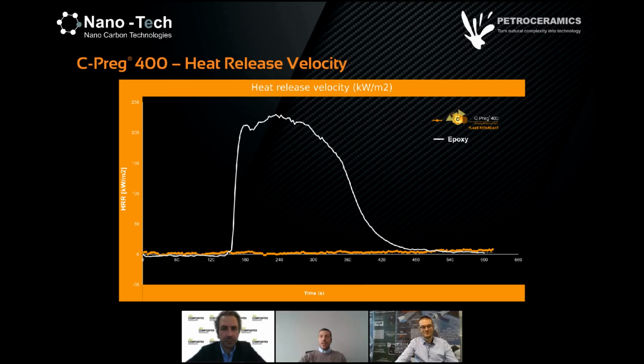Sorry, to interrupt, Andrea, just to clarify, what is the epoxy curve meaning compared to the Cpreg? Yes, sorry, the white line is the epoxy. As you can see, the heat release comes out after basically 150 seconds. That is the ignition time. And the Cpreg, that is the orange line, remains close to 0 for all the time of testing, that is about 10 minutes.